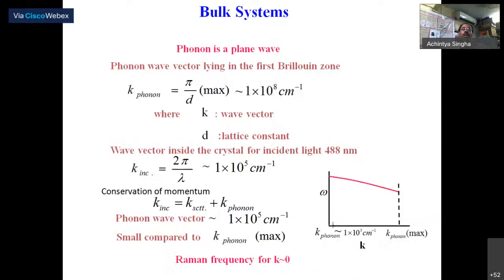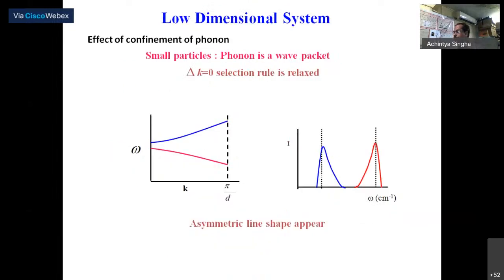Okay, in the bulk system, from the conservation of phonon momentum, the Raman scattering occurs at k equal to 0. So for a bulk system we get the phonon frequency at k equal to 0, which is the optical phonon mode. But in a low dimensional system, this k equal to 0 selection rule is relaxed, and phonons away from the zone center can participate in the scattering, and that will give you a change of the Raman line shape.